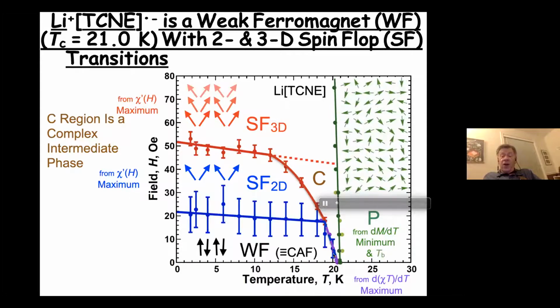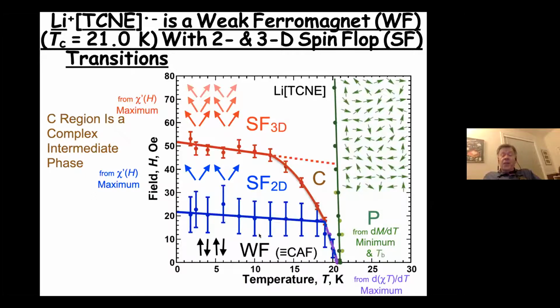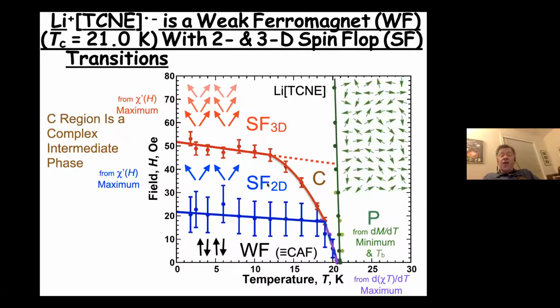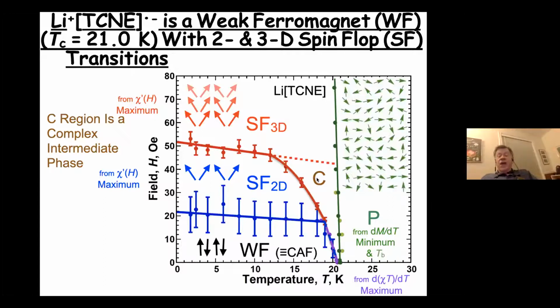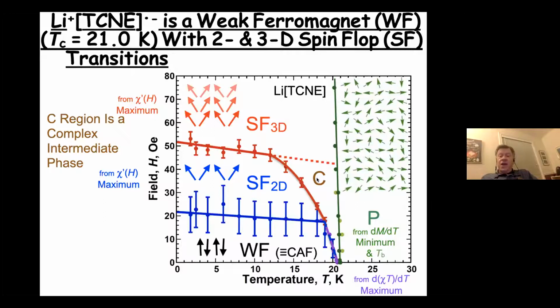And in low field, we end up with a weak ferromagnet. And we have in blue over here the transition to the spin flop in 2 dimensions. And at a slightly higher field, we have spin flop in 3 dimensions. And we have this region over here, which we've labeled C, which is clearly a very complicated interplay of all these phases, and that we don't fully understand. And this is sometimes seen for magnetic materials of this type.